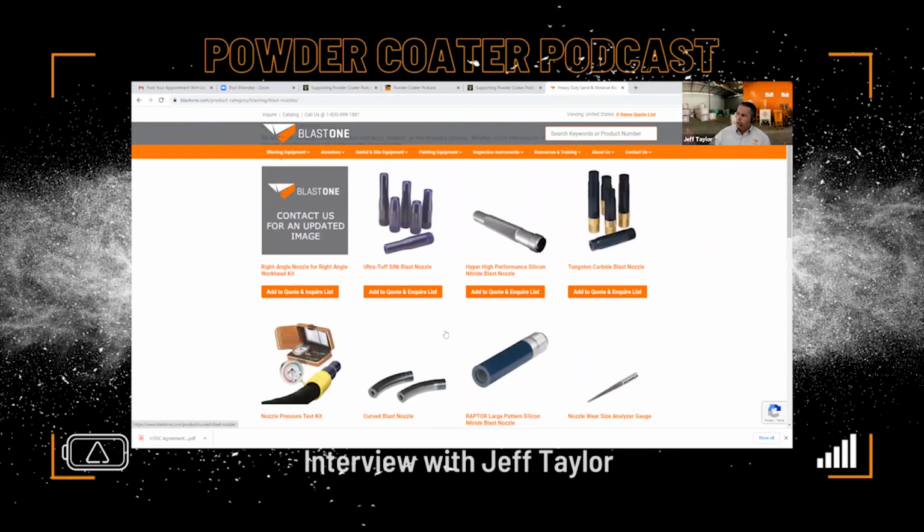The difference between a tungsten carbide and an ultra tough nozzle are a couple things. Tungsten carbide is a tungsten carbide interior. The ultra tough is a silicon nitride interior. Silicon nitride is going to give you double the abrasion resistance, so it's going to last you over twice as long. Another thing that's real common with the tungsten carbide is tungsten carbide is a brittle material. If you drop it, it typically cracks. And once you get a crack in your venturi, your nozzle, abrasive gets in there and ends up boring that crack out, and they wear out faster.